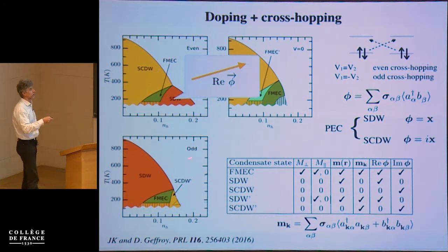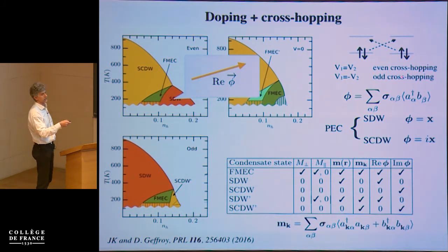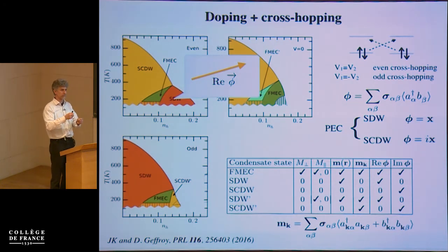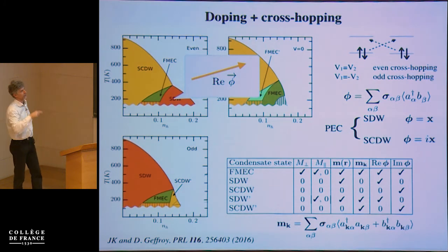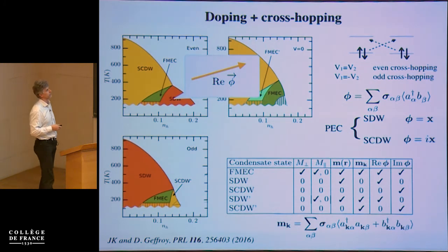If we start with odd cross-hopping, so if hopping to the left and hopping to the right has opposite sign, this is easy to realize geometrically. For example, if the A and B orbitals have an S-wave, S-like and P-like character, then the hopping between them would have different signs when you go to the left and when you go to the right.